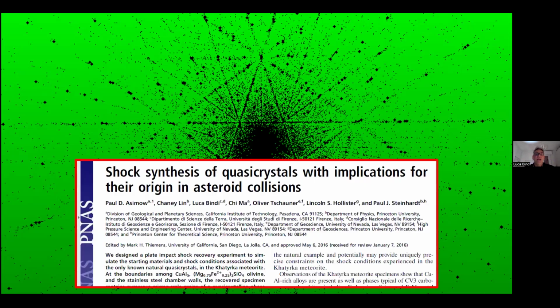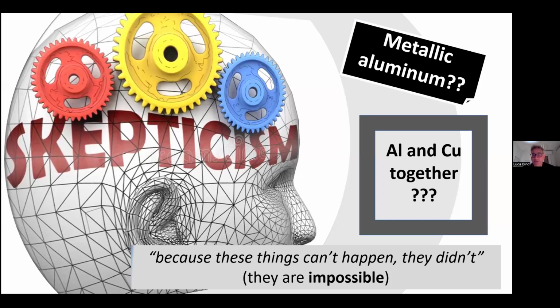And indeed, if you're interested in more information about these kinds of experiments, you can find all the evidence in this paper led by Paul Asimov and published in 2016 in the Proceedings of the National Academy of Science. But in spite of all the evidence we gathered in the last years, at that time we still had skepticism from the community. That skepticism was based mainly on the fact that we were reporting alloys with metallic aluminum inside. Metallic aluminum needs very reducing conditions to form, which are hardly achievable. But we have another conundrum, because we have aluminum and copper together, and they are completely geochemically different. Aluminum is lithophile, with strong affinity with oxygen. Copper is chalcophile, with strong affinity with sulfur. How did they come together? It was an enigmatic problem.